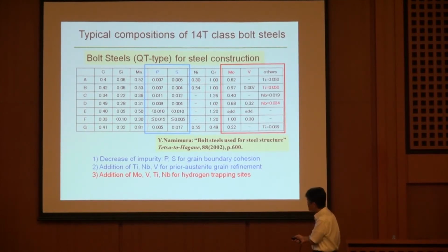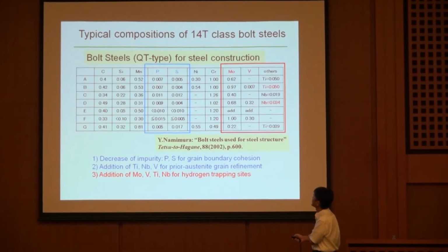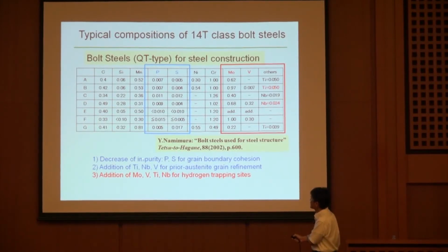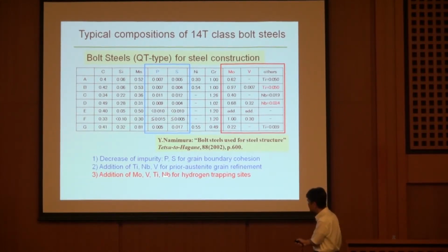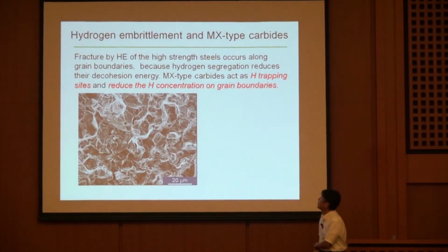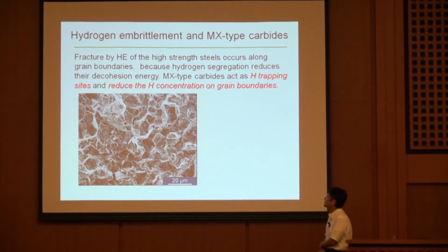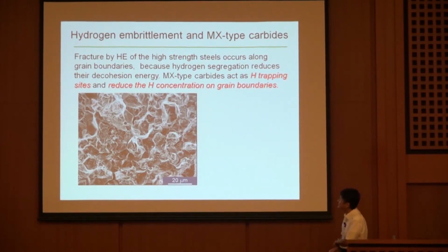So this is the list of characteristics of this new steel: decrease of impurities, addition of titanium, niobium, vanadium for prior austenite grain refinement, and addition of MX type carbides as hydrogen trapping sites. Hydrogen embrittlement fracture of high strength steel, where the strength level is higher than 1100 megapascal, occurs along the grain boundary because hydrogen segregation reduces the decohesion energy. So MX type carbides act as hydrogen trapping sites and reduce the hydrogen concentration on the grain boundary.